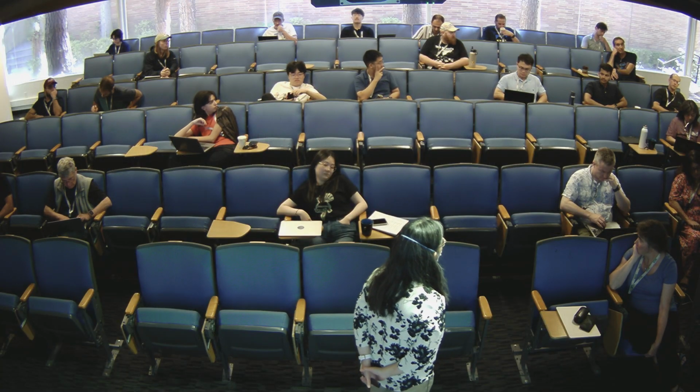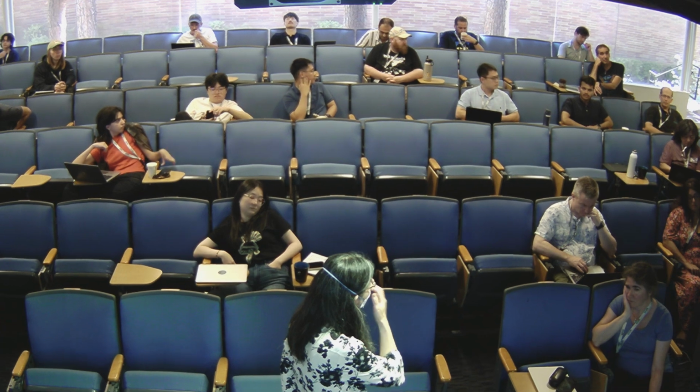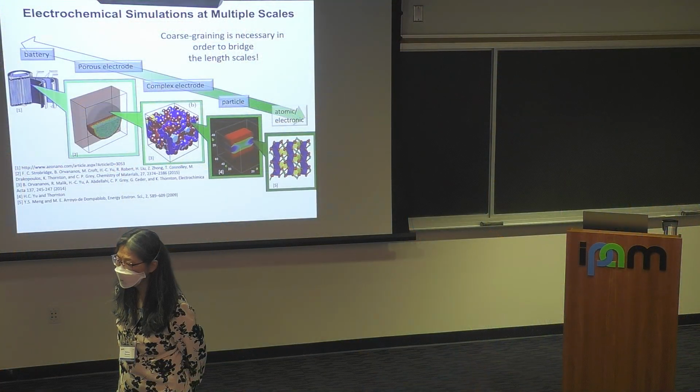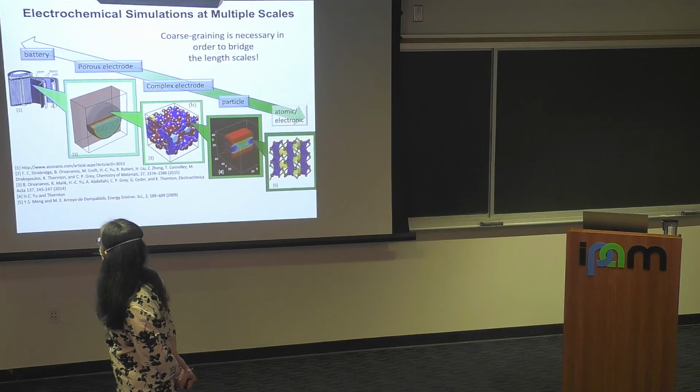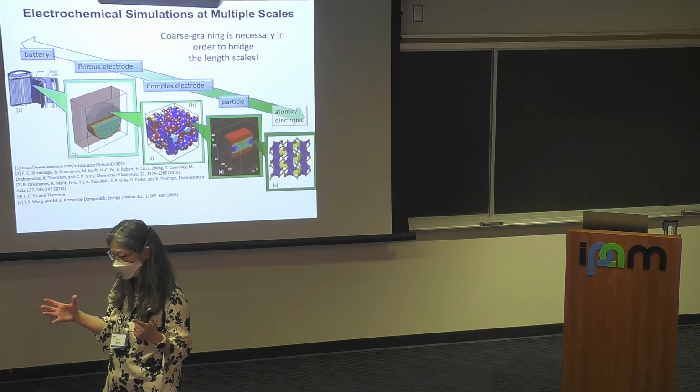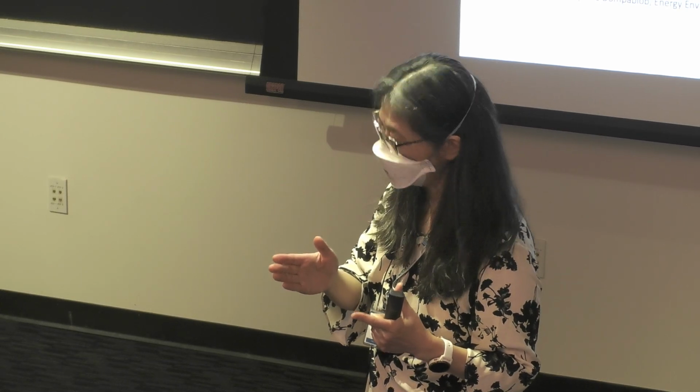I'm just curious, when you see this sort of wave phenomena, I guess at level 3, this complex electrode, where you see the small robbing the big of their lithium, is that a parasitic effect? Is that something you would like to eliminate, or is that something you can take advantage of? Actually, if the particle is large enough, then you'd have phase separation in the particle, which means you're creating interface, and that is probably bad, right?